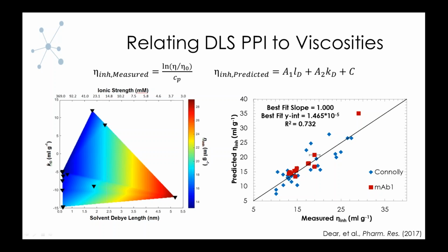So the same measured KD with a system that has less repulsion must also be less attracted. And we think that's what's going to have the main effect on the viscosity. As you can see, if you move left for a given KD on this curve, you get to lower viscosities. And that's what our data suggests from this interpolation here. Furthermore, we compared this with some data from literature.